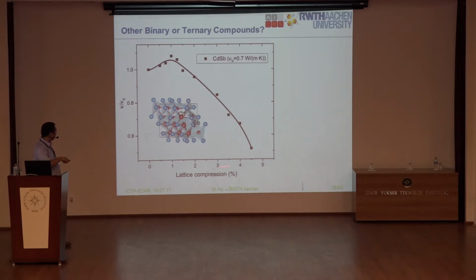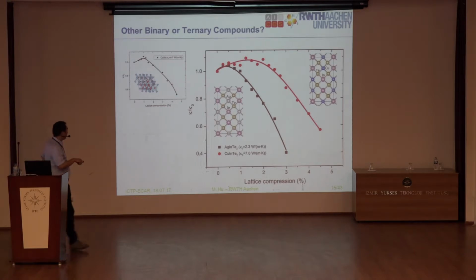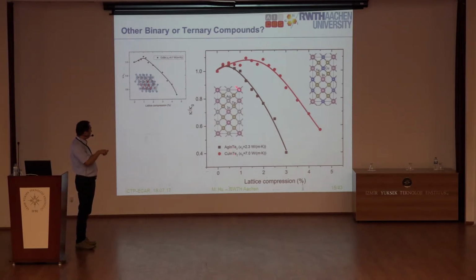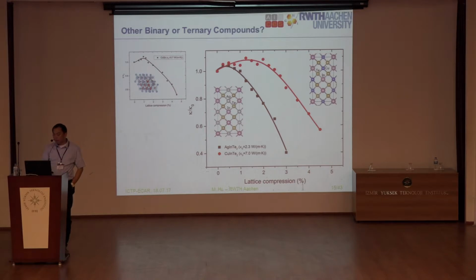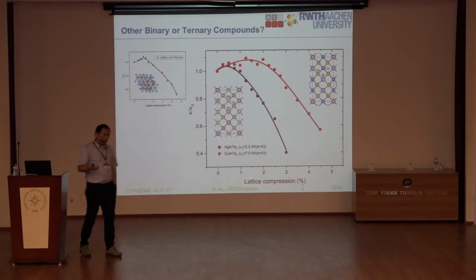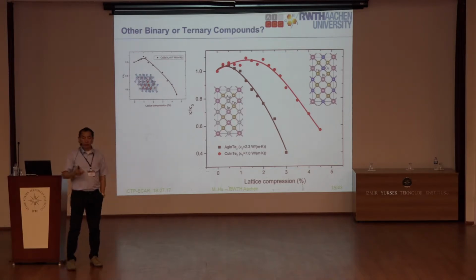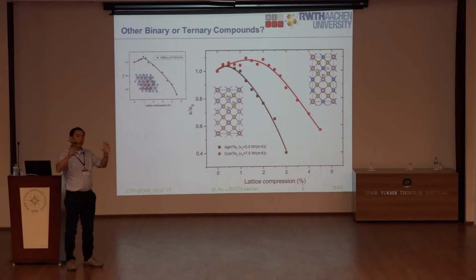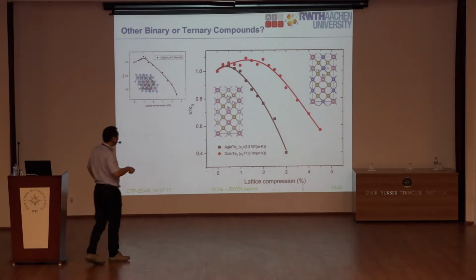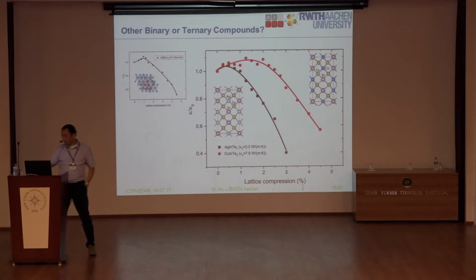If you increase the pressure, the lattice compression increases, and the thermal conductivity goes up a little bit and then drops down quickly. This is a binary, and then you also have some other ternary compounds, silver indium telluride or copper indium telluride, where you also find a similar significant decrease, the same behavior. So now we are analyzing this, and from a material design point of view, maybe we can produce some criteria to identify, if you have a structure and some atomic index, that you can predict in this material a negative pressure dependence.